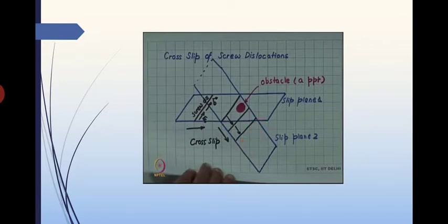We have studied that the more dislocation movement there is, the more ductile the material will be. That means straining will be happening easily. If we are able to stop the movement of the dislocation, whatever dislocation it is, then the material becomes harder.